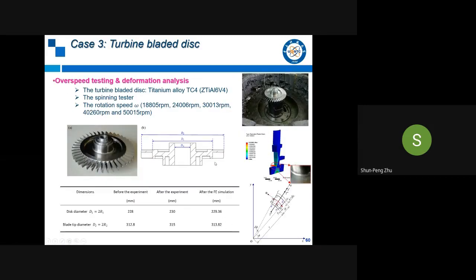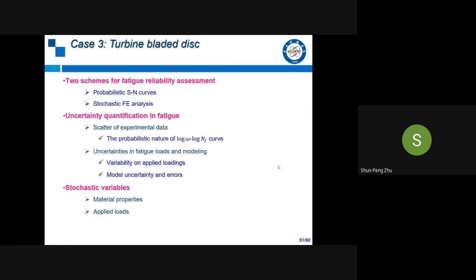Here is the overspeed spinning tester. For this one we tested at five load levels, and we measured these two dimensions, D1 and D2, before and after the experiment. We also analyzed it with FE simulation and compared the results here. After the final test, we found accumulated plastic deformation at the bottom of the turbine disk. And here are similar results based on the schemes mentioned before.